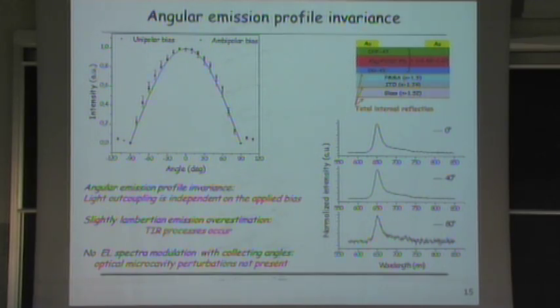This proves that the effect of the electrodes in our structure is not so important. It is not so relevant. There is a slight Lambertian emission overestimation here at more or less minus 70 degrees due to total internal reflection, but also the electroluminescence is not modulated at different angles. So this demonstrates that there is no optical microcavity perturbation inside, like usually is present in OLEDs.